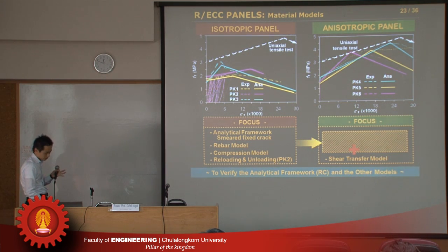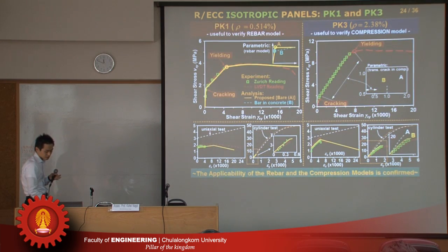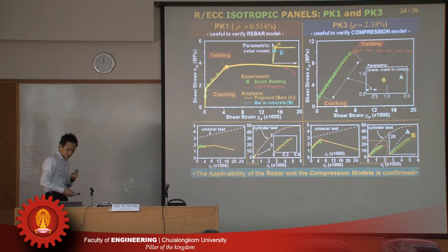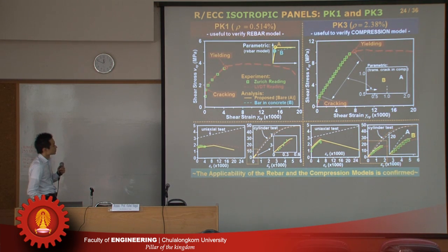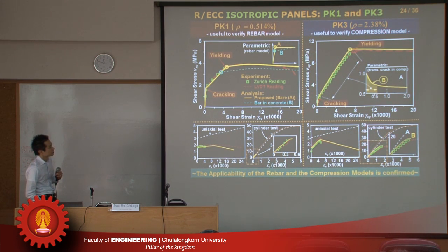So from the experiment, we extract the tensile material property and apply it to this test. And this is a case with the same reinforcement ratio. This is the experimental result, and the yellow one is the simulation result. That agrees very well. And yes, this is the case